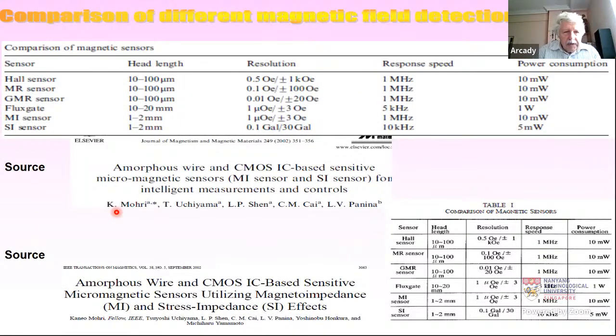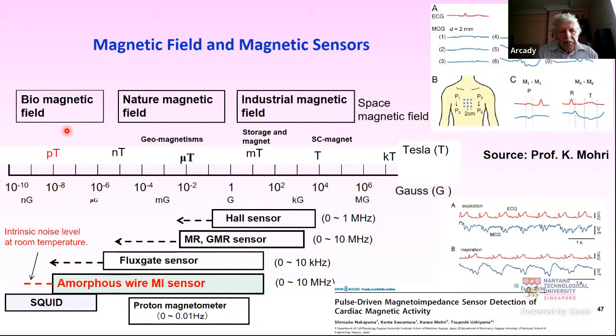And there were different papers comparing properties of different magnetic field sensors. So MI sensors are quite good. The only problem was the size. And recently, because of the thinner wires developed, for example, by us, the size could be drastically decreased. And this gives us a possibility to measure a very small magnetic field, because magnetic impedance has quite high field sensitivity, even to biomagnetic fields.